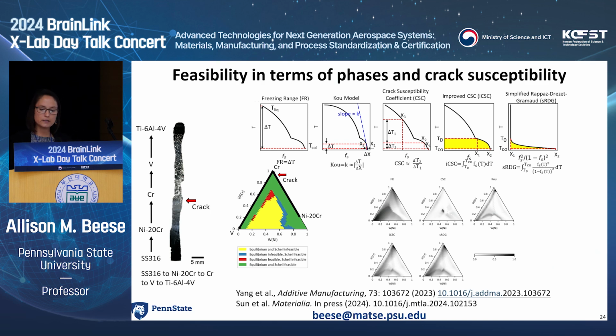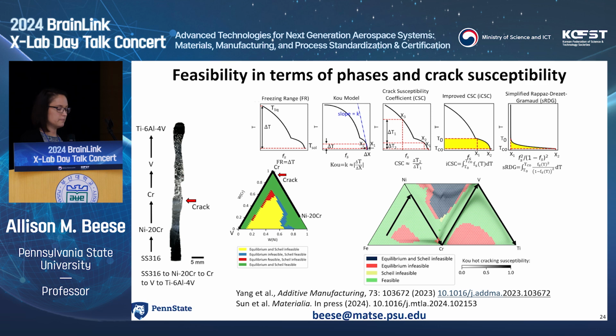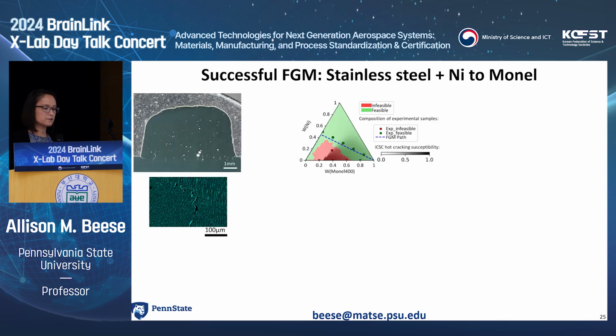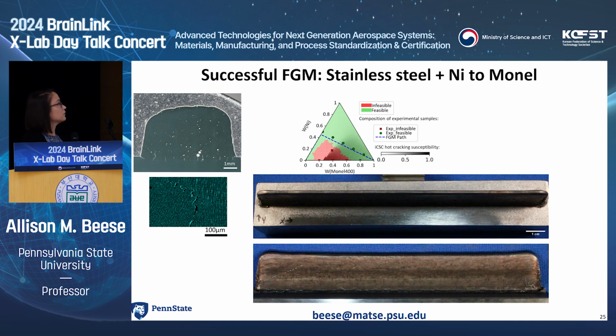So we can now merge these two techniques together and say, okay, we have now a map that would tell us where to avoid compositions based on intermetallic phases. Those are the colors. And then the grayscale on top of that would tell us regions to avoid if we want to avoid solidification cracking, or things that we would need to modify our processing parameters. So we've used that to successfully grade stainless steel to Monel. If you try to merge these two directly, you'll get cracking due to copper segregation. But if we add in some nickel to avoid the crack susceptibility region, we're able to successfully grade between those two components.